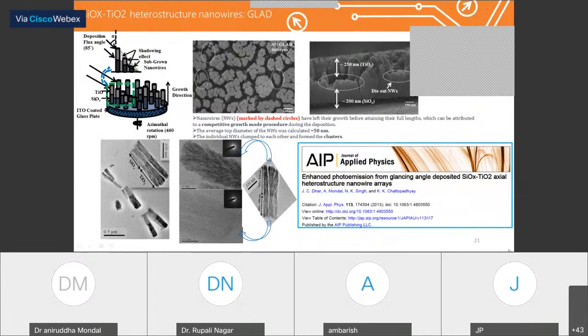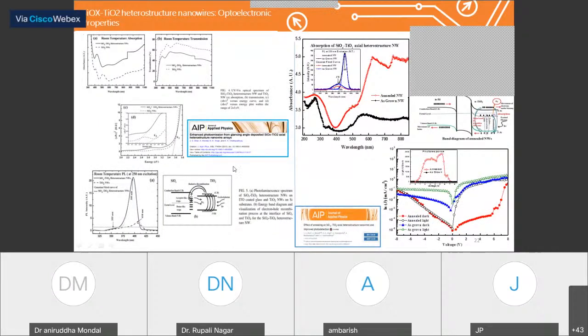We have seen that this kind of nanowires are very important for the fabrication of junctionless LEDs, because the titanium dioxide and the SiOx have several defect states. When it is excited from the outside, the titanium dioxide has electrons which go to the conduction band, and the conduction band electrons start to move to the silicon monoxide side, and they are recombined with the holes at the junctions of the silicon monoxide and titanium dioxide, and they are radiatively recombined, and a photon is generated. So this shows from the PL curve how the photon has been generated more.